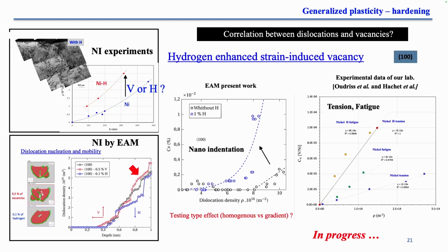And to check that, we use EAM atomistic calculation and show the evolution of the density of dislocation as a function of the depth. The red curve is with vacancy, the blue curve is with hydrogen, and the dark curve is without anything. And we show that hydrogen decreases density of dislocation, and the vacancy increases density of dislocation, which means that the vacancy produced is responsible for the increase of the density of dislocation.